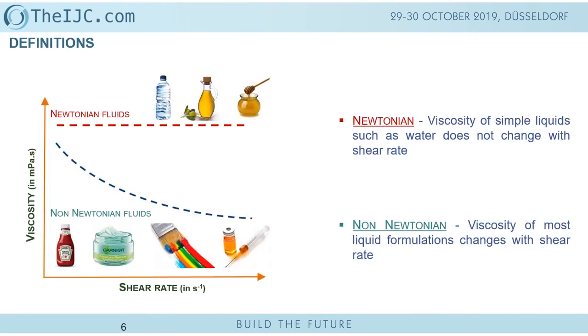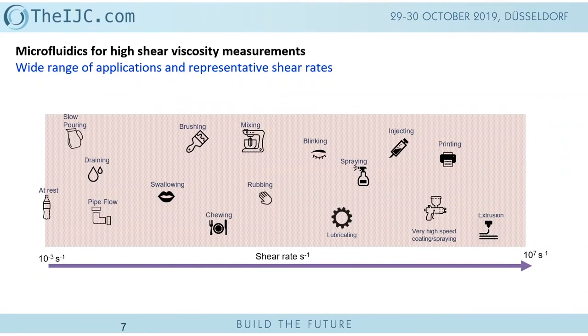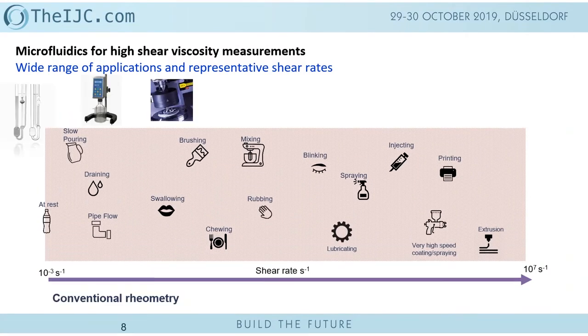In nature we usually encounter Newtonian samples where the viscosity never changes as a function of shear rate. On the other side, we have non-Newtonian shear thinning profiles where the viscosity decreases as we increase the shear rate. There is a large range of applications across the shear rate scale, going from rest — about 10⁻³ — to 10⁷ reciprocal seconds. Conventional rheology tools typically operate at lower shear rates, with the highest reaching about 4,000 reciprocal seconds.